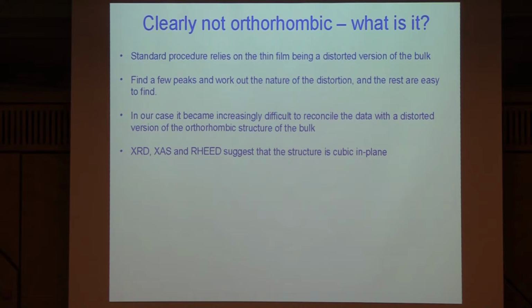Well, normally what you'd do is you'd take the bulk structure that you think it is and try and twist it and distort it to fit your X-ray peaks. That's what you'd normally do. And you'd find out a few peaks and try and work out the nature of that distortion, and the rest is easy to find. But it just didn't work. We couldn't make that work at all.